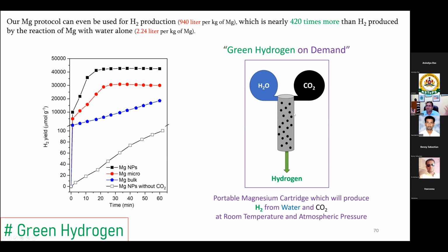And now think about a dream apparatus or device where I have these cartridges filled with magnesium powder - again, no nano, bulk scrap magnesium. Then I have two tanks, one with water, another with CO2. You mix water and CO2, add it into the magnesium cartridge, and you produce hydrogen. The flow of hydrogen can then be tuned by the flow of CO2 and water. A very simple system - we're trying to find a collaborator to build it.